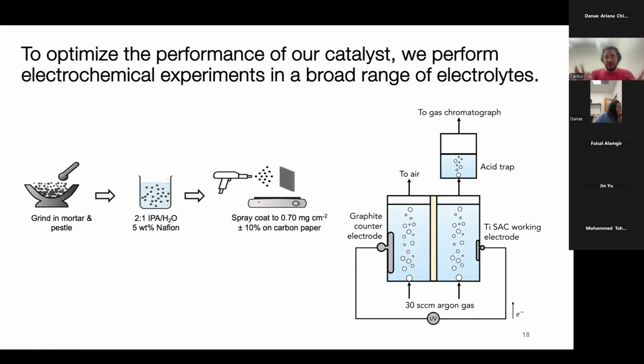Now that we have fully characterized our catalyst, we will do the electrochemical characterization of it because we want to figure out what are the best electrolytes and in which conditions this catalyst performs the best. To do this, we first grind our catalyst with a mortar and pestle because it agglomerates into bigger chunks and we want to make it into a fine powder. We disperse it in IPA, we mix it with Nafion, and then we spray coat it onto carbon paper.